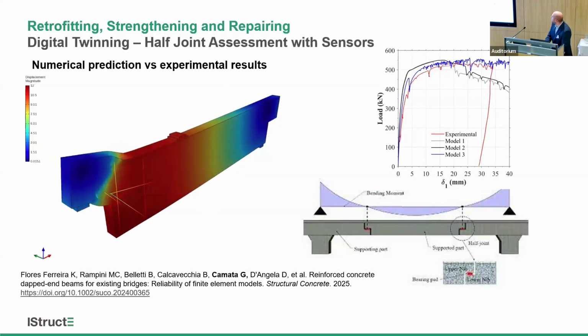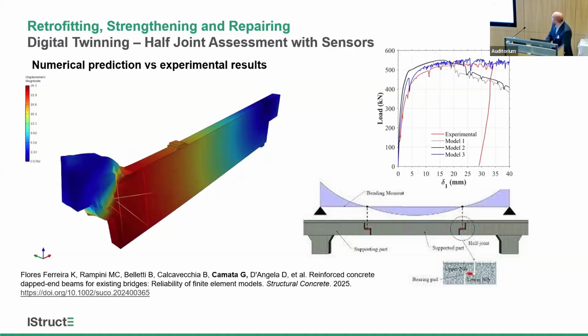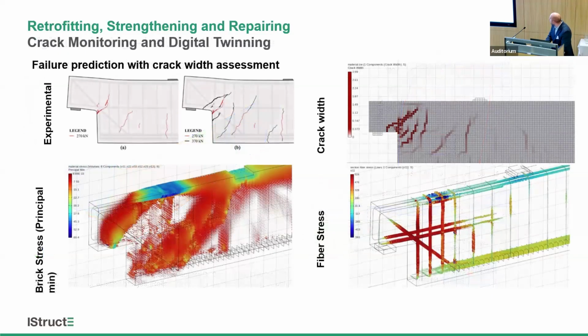This can be used in research, for example, modeling of a half joint. It can be used to create a numerical model that's able to predict the failure and align this with the laboratory data and the monitored cracks. So this is the same half joint, and you can see the cracks that were measured in the laboratory tests, and you can see that the nonlinear analysis is able to replicate these. So in this case, crack monitoring was used on the live specimen, and that was fed in to help predict the formation of cracking. And then that was used to predict the failure of the half joint.